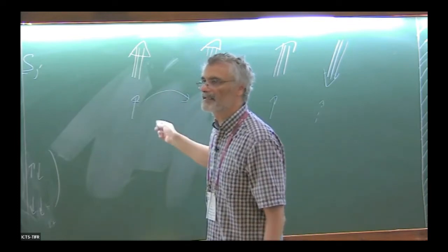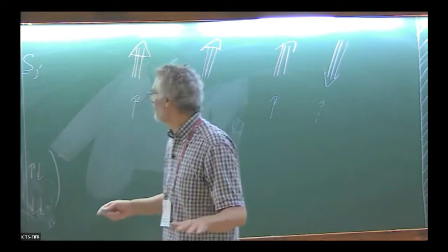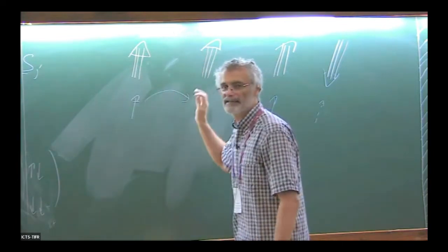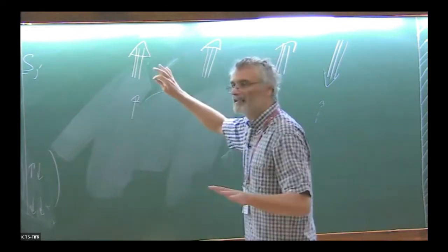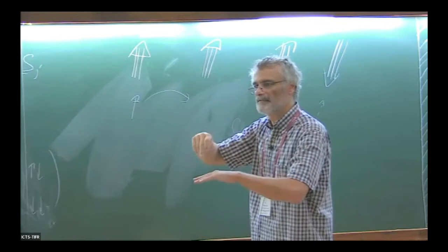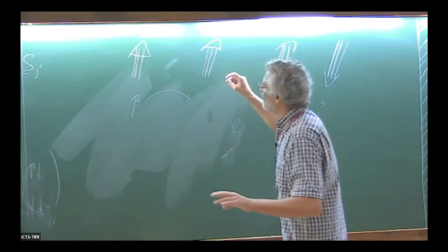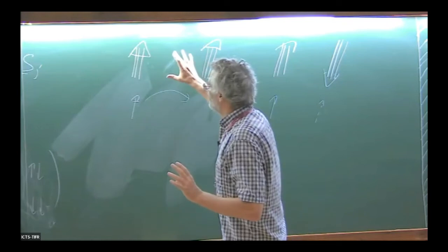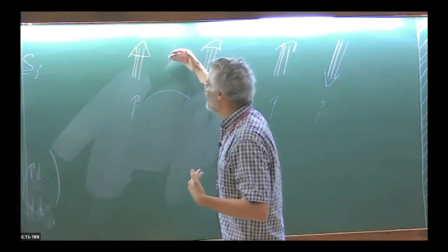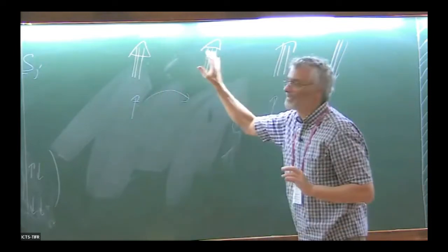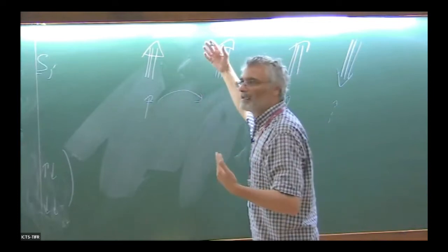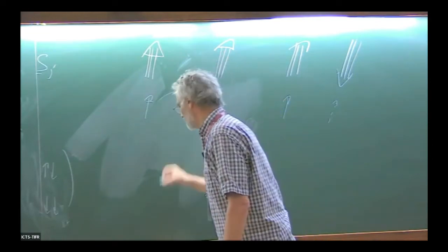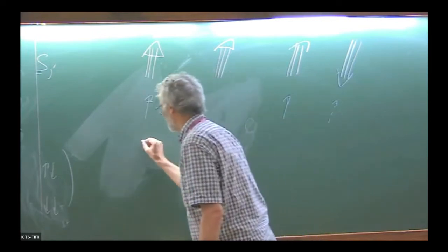This double exchange is something that is used in hard drives. So this is the mechanism. If you make the head of your hard disk from a material like this, then depending on the magnetic field of the plate below, I know today we have SSDs, but earlier, the resistivity would drastically depend on the magnetic field, because the magnetic field will interact with these localized spins and try to make them more ferromagnetic, and it will decrease the resistivity, increase the conductivity. And these materials have so-called colossal magnetoresistance.